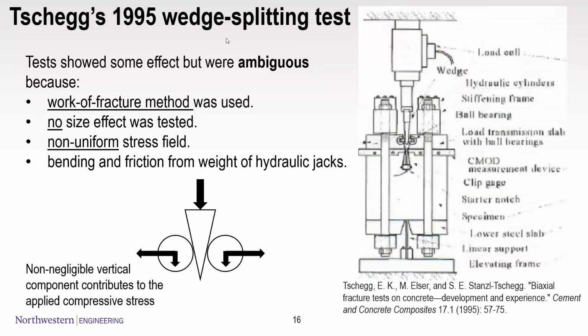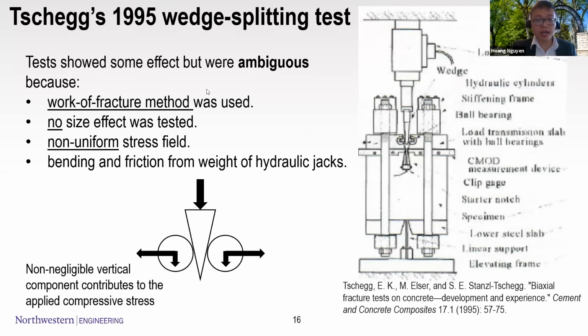It's worth mentioning that there were some attempts at a similar idea. However, for Tschegg in 1995, he developed some early ideas of the test in 1990, and then finalized and perfected the design using the wedge splitting along with the second fixture to apply the crack-parallel stress on the wedge splitting specimen. However, in this case, you can see that it is a work of fracture method. It means that it requires full measurement of the load displacement curve of the crack, or load crack opening displacement curve, and no size effect was tested. And I will mention size effect later and how it matters.